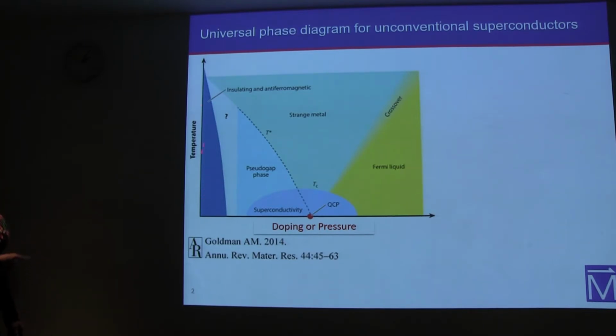At low tuning parameter, low doping or pressure, they start with an insulating phase, and most of them are antiferromagnetic. Then as you increase the doping or the pressure, they become more metallic, either with a strange metal phase or at higher doping a Fermi liquid, so a standard metal. They develop a superconducting dome, one or several domes, most often stabilized around the quantum critical point or several quantum critical points, and the reason for that is still unknown and subject of investigation. So the object of our work is to look at those unconventional superconductors and try to see, by pressure actually, and looking at high magnetic field, what can we learn from those systems.